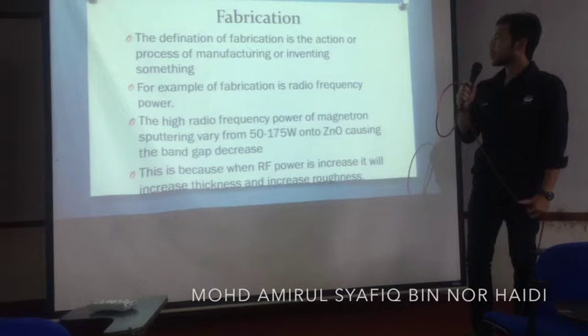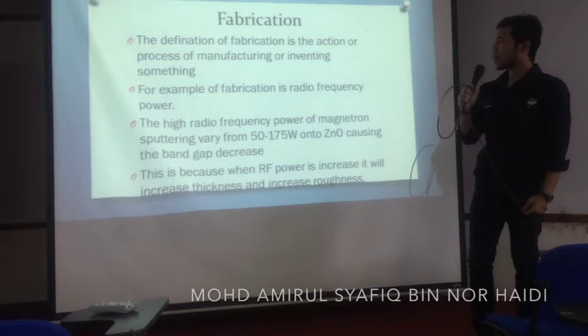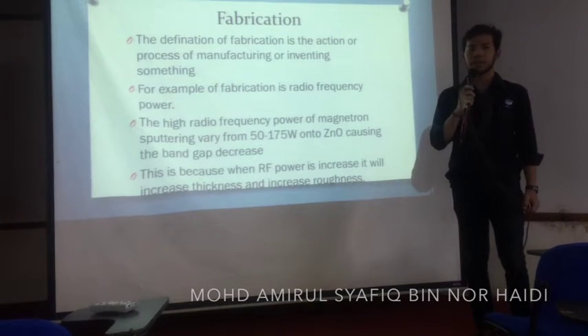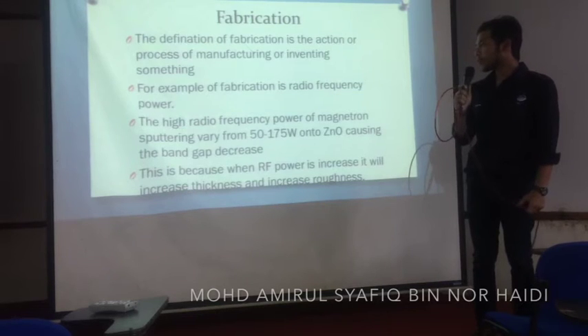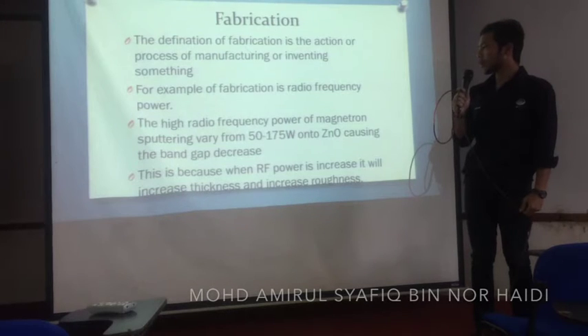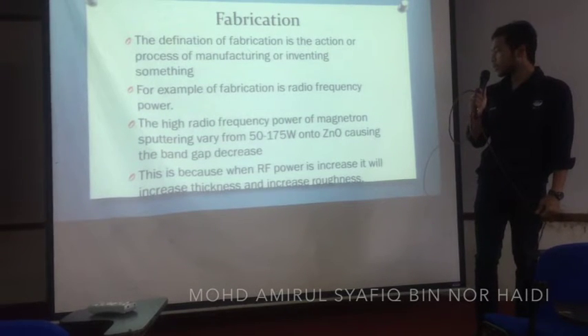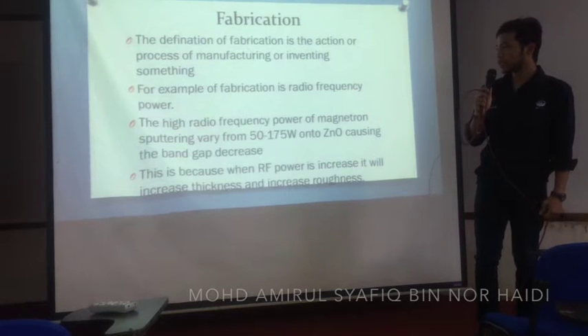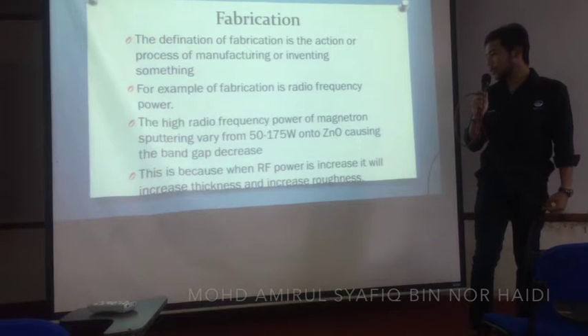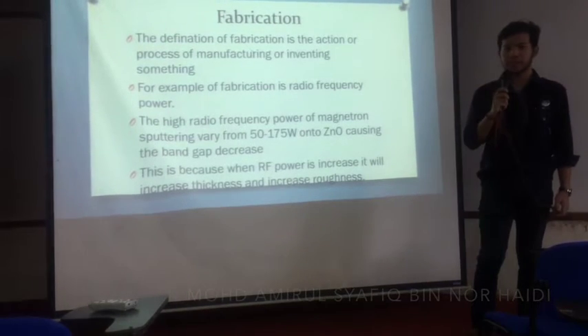Last is fabrication method. Fabrication is the action of manufacturing something. An example of a fabrication parameter is radio frequency power. High radio frequency power from magnetrons, varying from 50 to 175 watts applied onto zinc oxide, will cause the band gap to decrease. This is because when radio frequency power is increased, it will increase the thickness and roughness of the object.